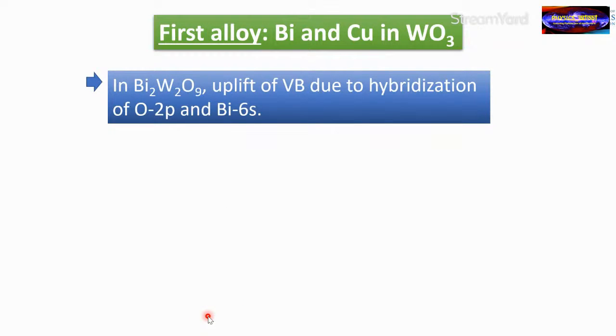After we did testing, we decided that bismuth and copper can be put in tungsten oxide to make a new alloy. Now, why bismuth and copper? These are a few simplified reasons. In bismuth tungstate, we found the valence band uplift takes place because of hybridization of oxygen 2p and bismuth 6s electrons. This hybridization has a name. It's bonding, antibonding, and these s electrons are called lone pair electrons. The lone pair electrons have some special properties.